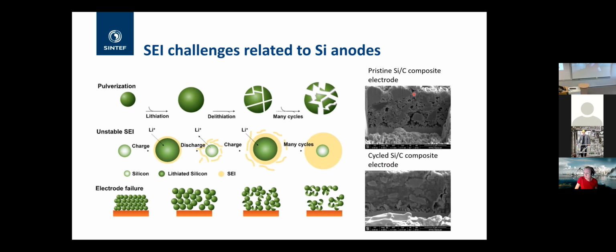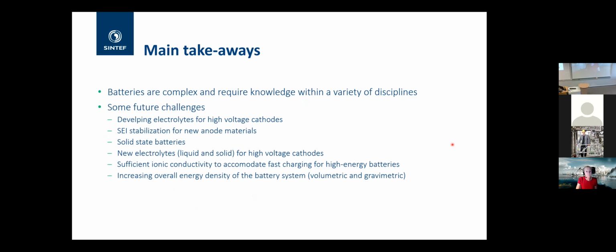The SEM images, so the microscopy images to your right here, show an electrode where the top one is a pristine electrode. The bottom one is an electrode that's been cycled. And this shows how the SEI just fills up the voids in your structure. This is a composite with silicon and graphite. So the SEI problem and the expansion and cracking problem of silicon are really big issues that people are trying to solve. Sorry, Fride, we're running out of time.